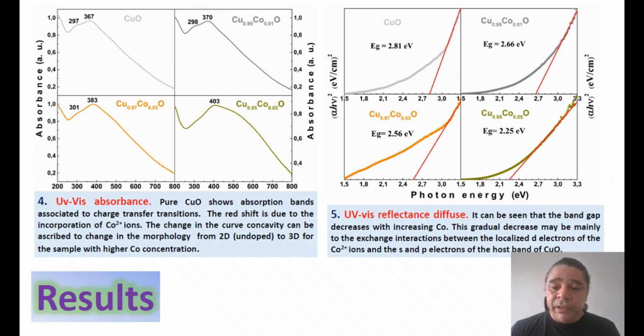We can see that the band gap decreased with increased cobalt concentration. This gradual decrease might be due mainly to the exchange interaction between the localized d electrons of the cobalt 2 plus ions and the s and p electrons of the host band of the semiconductor.